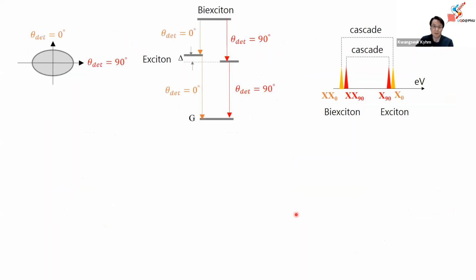Okay, so another interesting, surprising feature is the selection rule. If you're familiar with quantum dot elliptical shape, we define the two principal axes, 0 and 90. And regarding the cascade transition from the biexciton to exciton, you know, the angle is 0, 0, and 90-degree, 90-degree. So you will get such a pair with the 90-degree selection and the orange one. So this is the cascade pair for the typical elliptical quantum dot.